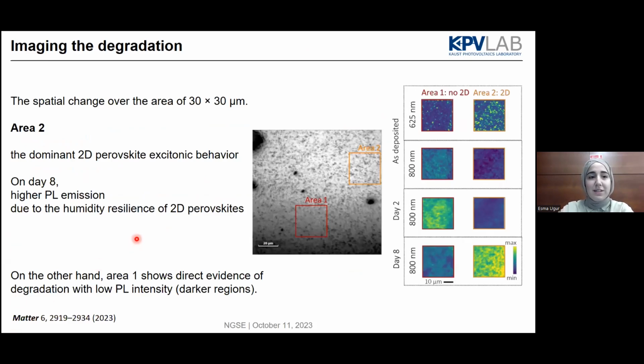So this is one of the nice things that you can see. Here is the sample's optical microscope image, and you can see that area 1 and area 2 show different formation of these 2D. Let's say for area 1 you don't have too much 2D formation, but for area 2 you have quite a lot of excitonic peaks. And this is because of the parasitic absorption of the 2D, that you see darker for the PL peak position of the 3D perovskite.